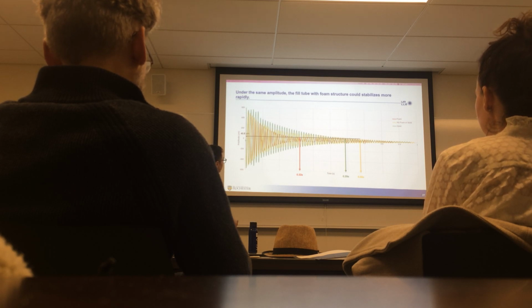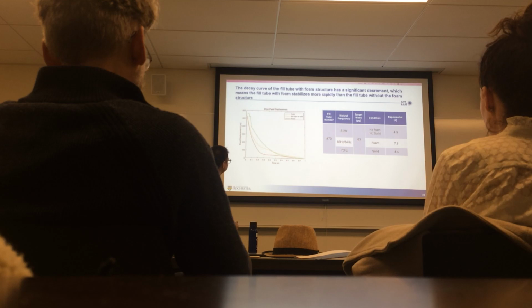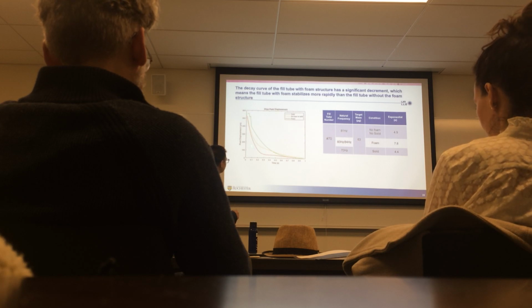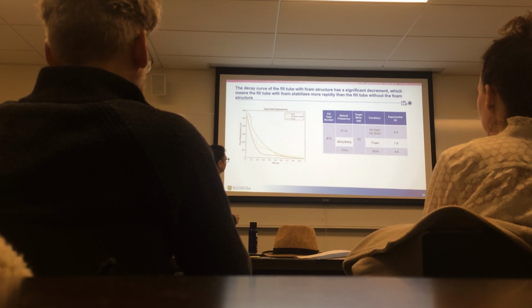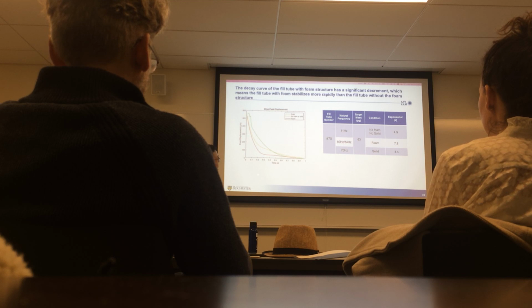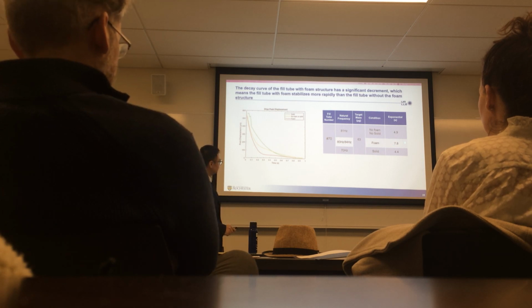And if we compare the decay curves, the red curve is for the fill tube with the foam structure, and the green curve is the fill tube with the solid structure. In the center, the yellow one is the fill tube with no foam, no solid, just the target structure. We find that the one at the bottom is the fill tube with the foam structure. It has a significant decrement, and our exponential values also prove that.